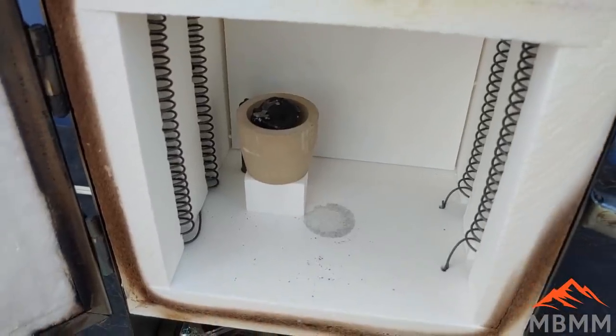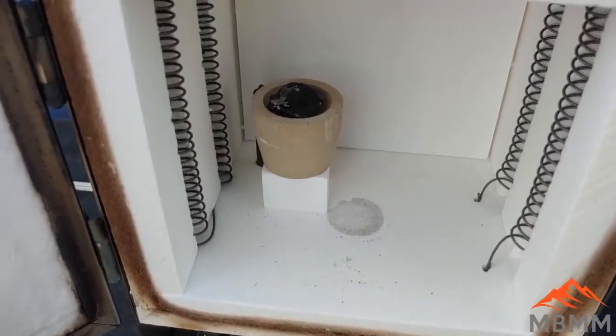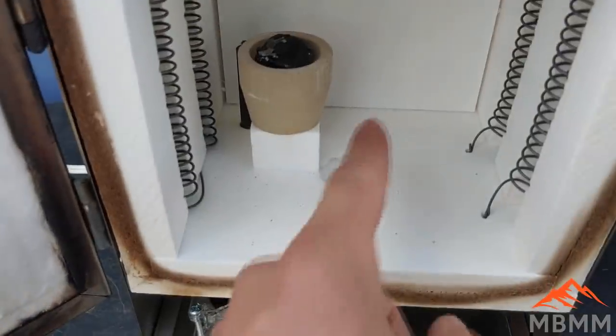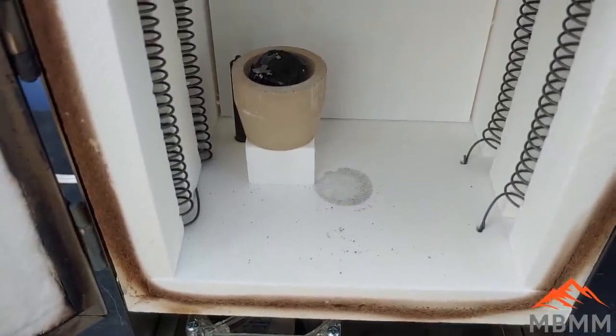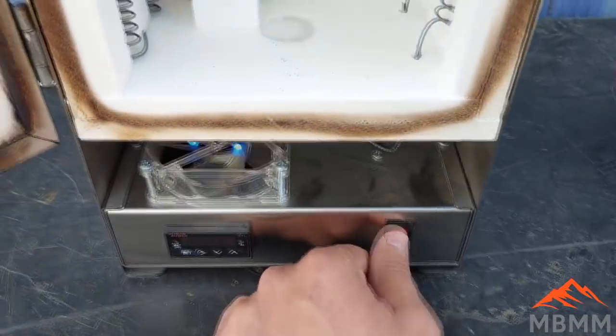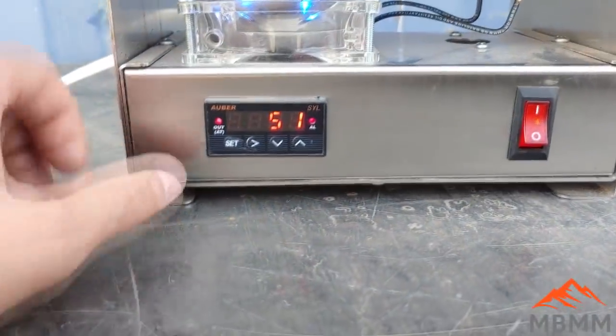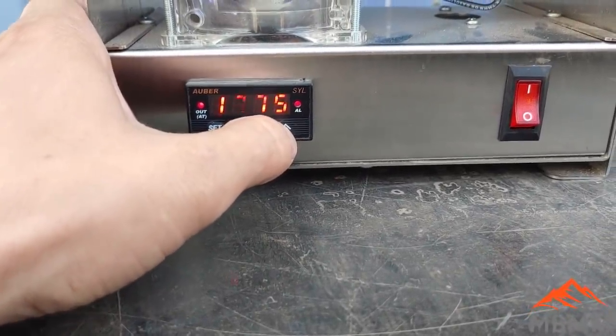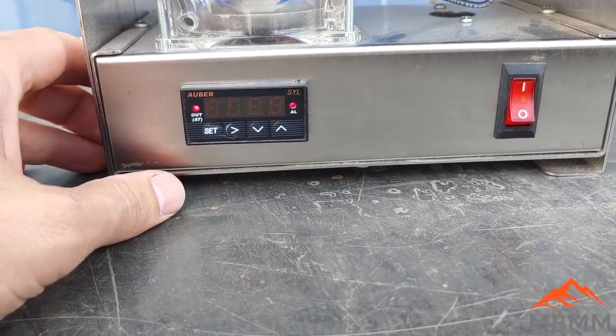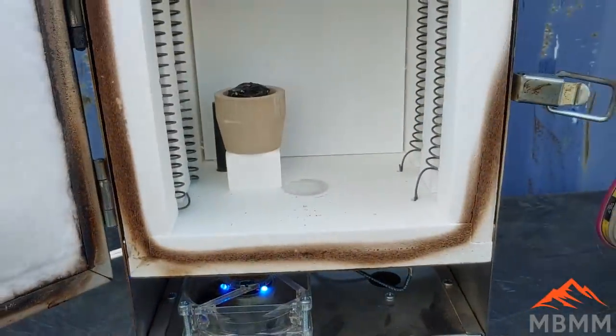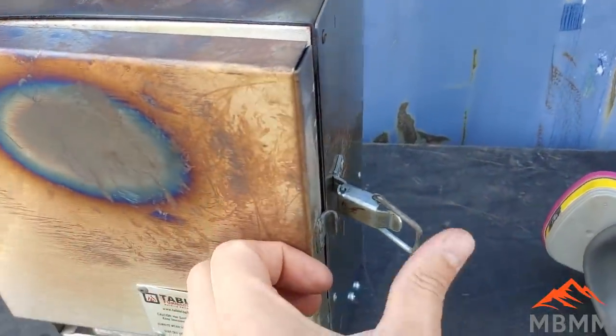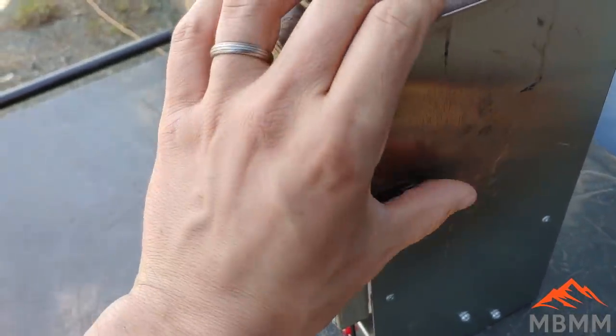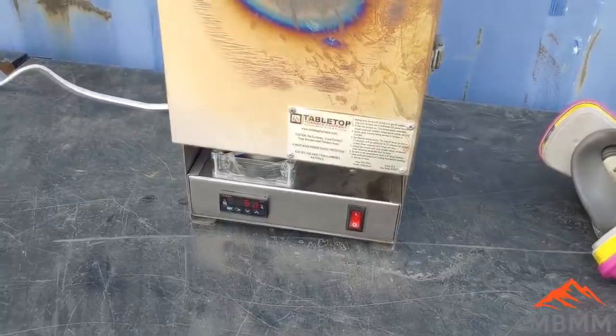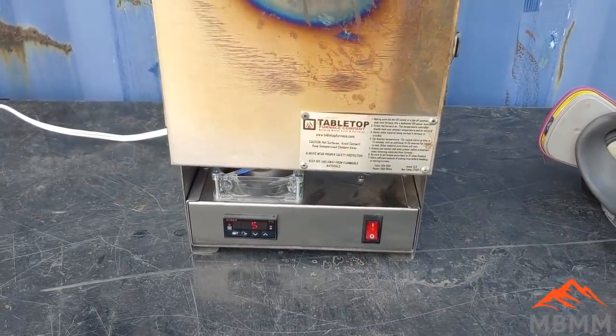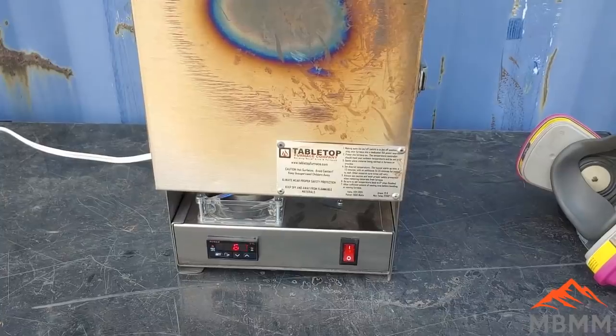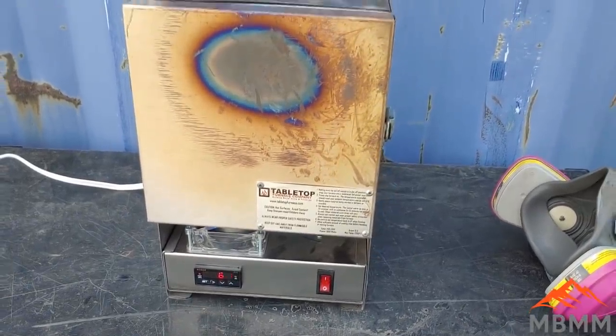Here's our first cupel in our little electric furnace. I moved it over so if I need to, I can put another one, and actually I can probably run 4 or 5 in here at the same time. But this is a pretty nice little furnace. You click it on, you can set your temperature. It remembers my temperature from last time, so 1775 is what we're going to do. I'm going to close the door and latch it, and let it heat all the way up. And then I will crack the door and let some oxygen in once it heats up. So we'll check back on this in a couple minutes and see how it's going.